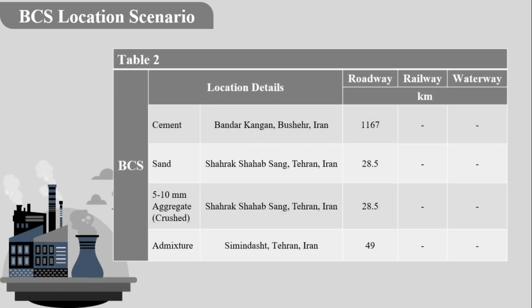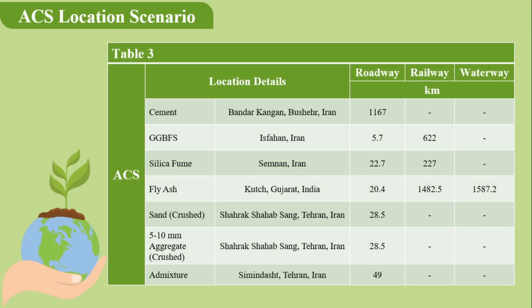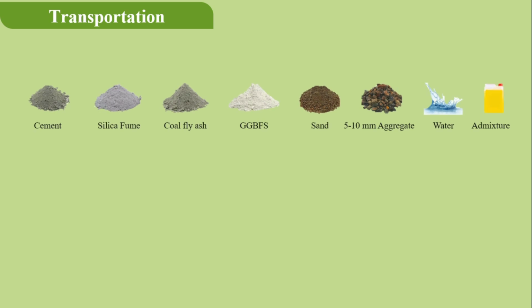The cement used was selected from the Kangan cement plant, which is one of the suppliers for Tehran city. Crushed aggregates and the admixtures were also sourced from one of the nearest producers. For SCMs, silica fume was selected from Semnan, slag from Isfahan, and fly ash, due to the lack of domestic production, was selected from Gujarat, India. The details of transportation routes are presented in the following slides.